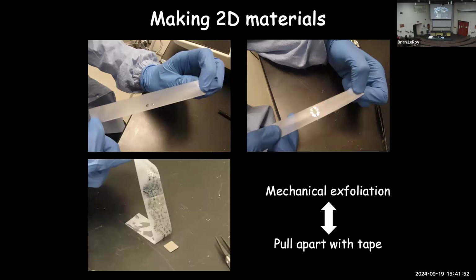So how do we actually make these materials? We're still making them the same way that they were made in 2004, with a technique called mechanical exfoliation, which is just a fancy way of saying that we take Scotch tape and peel apart the materials. Here's a picture of one of these crystals on a piece of tape. You fold it in half, and because it's a van der Waals material, it likes to break apart into two different sides. So you go from something that is maybe 1 millimeter thick to two pieces which are 0.5 millimeter thick. You repeat the process, getting half as thick each time.